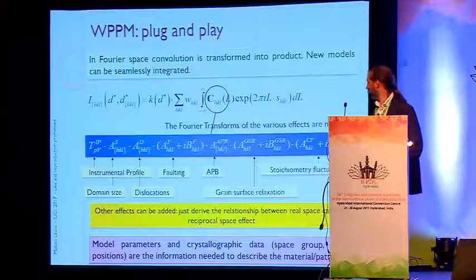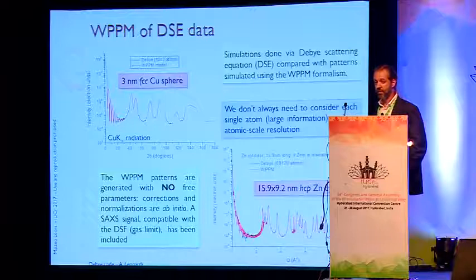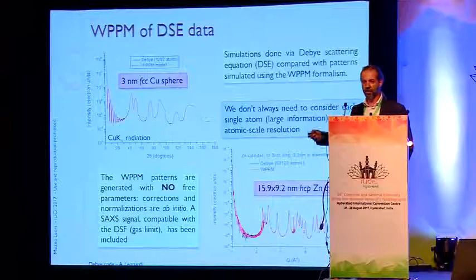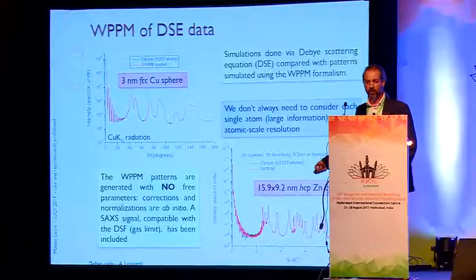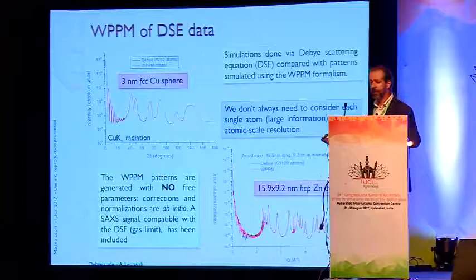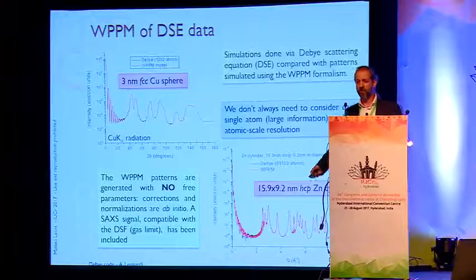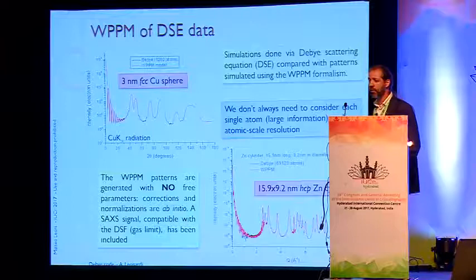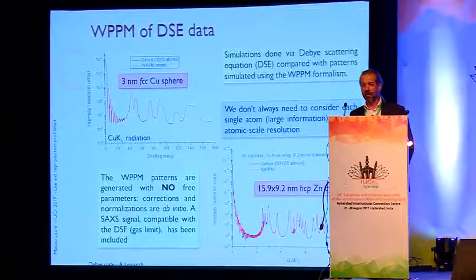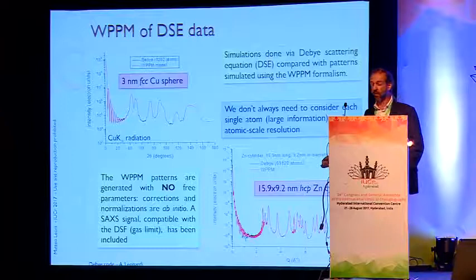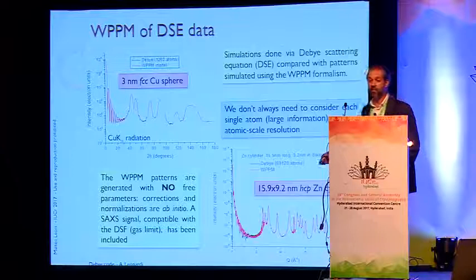Does it work? Usually this is the question — how do you pretend to have atomic resolution when you're putting atoms aside and saying it's an average system with a shape function? It actually seems to work quite well. We generated some spheres atomistically rough, calculating the diffraction pattern using the Debye scattering equation — that gives the exact diffraction pattern — and did the same model using the WPPM approach, convolving all effects calculated analytically. The match is quite good. You don't see this kind of atomistic roughness. You're modeling something physical using a very fast algorithm that scales with the number of peaks, not with the number of grains. That could be a great saving of time.